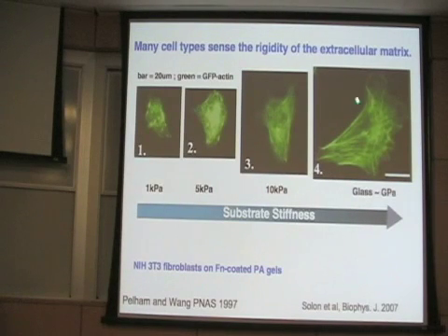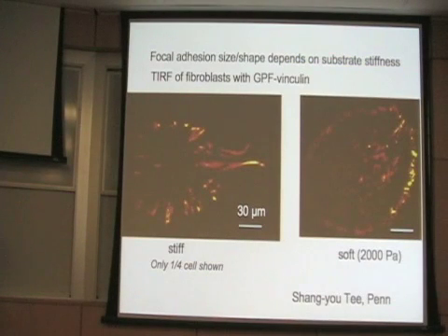We've seen several examples of this, and this field was largely brought back to life by a paper by Pelham and Wang about 10 years ago. This is our version of their experiment, where they looked at simply the actin cytoskeleton, or the morphology of the cell. This is a garden variety fibroblast grown on matrices very similar to what Cindy King showed us a little bit ago, that this increase in elastic modulus causes these types of cells to spread more and to start assembling stress fibers. So we've looked at other aspects in other cell types, and here's one example of what we've started to look at lately. This is work by a new postdoc, Shang-you Tee, who has learned to do total internal reflection fluorescence from the interface between a soft material and the aqueous substrate. In this case, it's a very lightly cross-linked PDMS substrate.